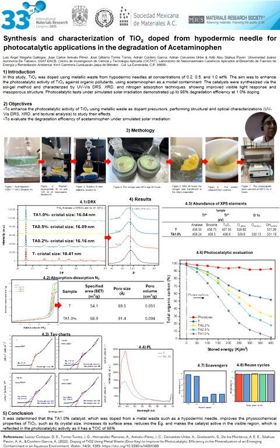0.5, and 1%. We know that titanium dioxide is one of the most used semiconductors in photocatalysis because of its photocatalytic properties. However, by itself it has some problems, like it only works under UV light and has a band gap of 3.2 eV, which makes it easy for electron-hole recombination. That's why many strategies are studied to improve the physicochemical properties of titanium dioxide, like doping.